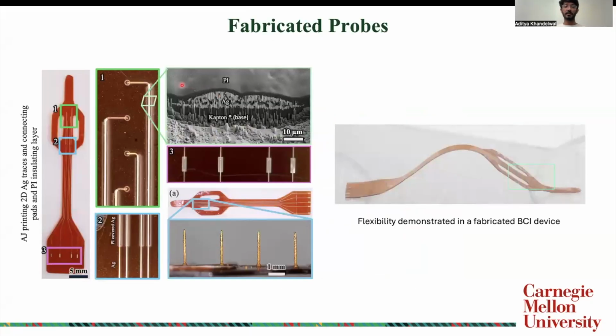On the left, you can see the fabricated probes. These are the silver tracks which are covered with polyimide, as you can see in this cross-section SEM image. The polyimide is used to electrically isolate the tracks so that cross-conduction of signal won't happen. The track pads are made wider so that they can be easily connected with an external device.